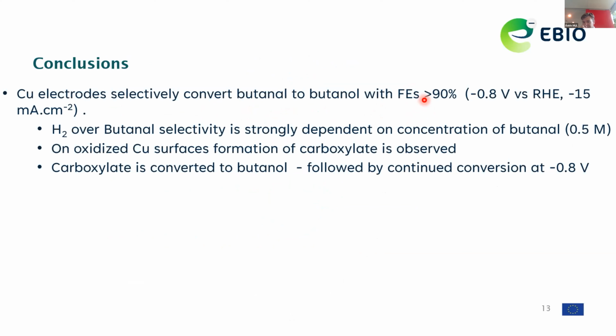Okay, so that basically brings me to the conclusions and maybe a little bit of an outlook of this work. So copper electrodes are very interesting if you want to do these hydrogenation reactions of aldehydes to alcohols. If the concentration of the reactant is high enough, half a molar gives Faraday efficiencies above 90% in comparison to hydrogen evolution. And here you see the characteristic voltage and current density. The selectivity is strongly dependent on the concentration.